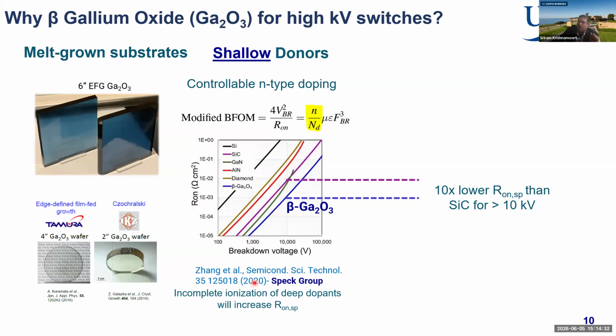And so the trade-off between the on resistance and breakdown voltage is actually worse for a material that has deeper dopants. This was worked out as a modification to the standard Baliga figure of merit in this paper from Jim Speck's group in 2020. Putting this together, it turns out that gallium oxide is quite a compelling case as the switch when you cross to much higher voltages, and especially having bulk substrates is appealing, and the shallow dopants are also appealing.